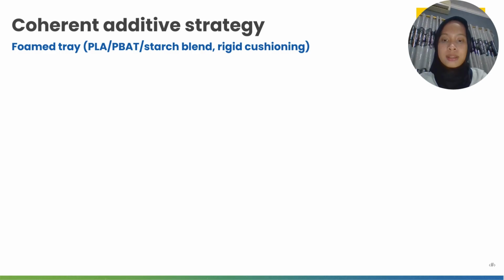For the last one, tray H, improve flame spread, drip and durability, the package is AO, chain extender, compatibilizer, nucleation and intumescent. And the coherency is that intumescent char reduces the flame spread and can help smoke, and foam stability improves. And the downside is it can wreck the foam, and with whiteness, brittleness can increase.